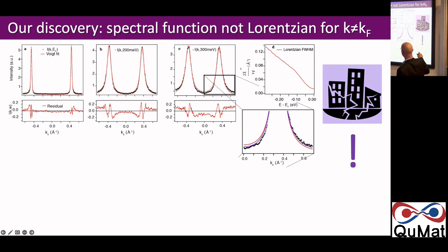So the residuals are getting larger and larger. It actually looks as if it's not what's happening. It's not the microscopic physics. You've taken these two peaks and essentially they're tilted a little bit outwards. So wrong way, in. So in between there, lower intensity than what you expect, outside they're not. So this means, that's why I have my earthquake logo.